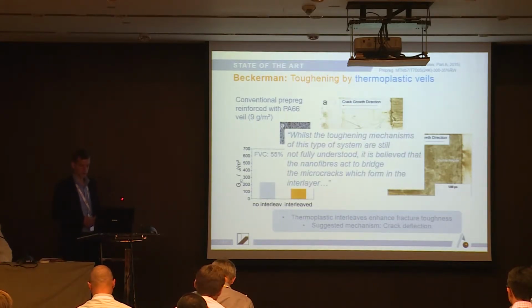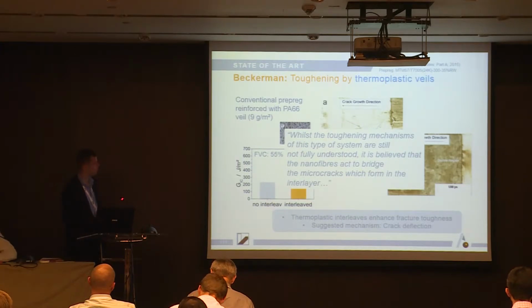And Beckerman said in his presentation that while the toughening mechanisms of these types of systems are still not fully understood, it is believed that nanofibers act to bridge the microcracks which form in the interlayer. So I don't want to go too much into detail, but the interesting thing is that the toughening mechanisms are not fully understood.